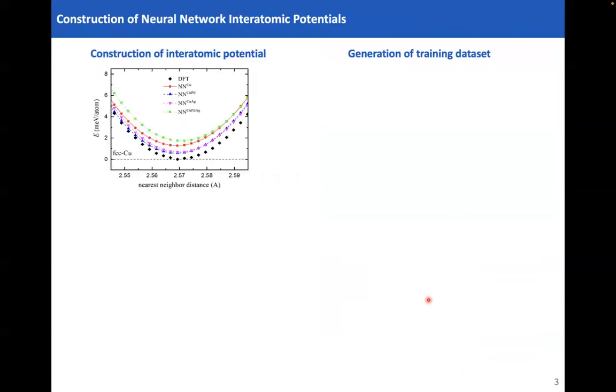So one problem that we might face is when we accumulate the data for various chemical systems and construct machine learning potentials. In this case, tests like the one that you are seeing here have shown that because of the different nature of bondings in different systems, as we mix these, we might get different descriptions for a certain element coming from different models.